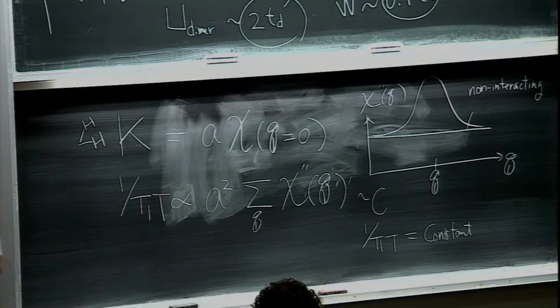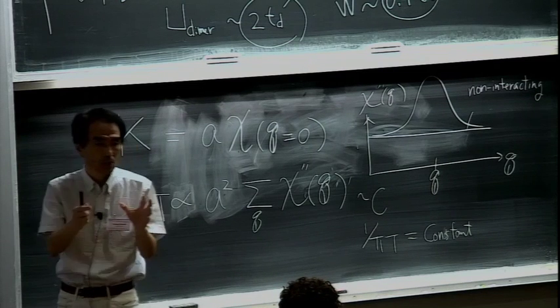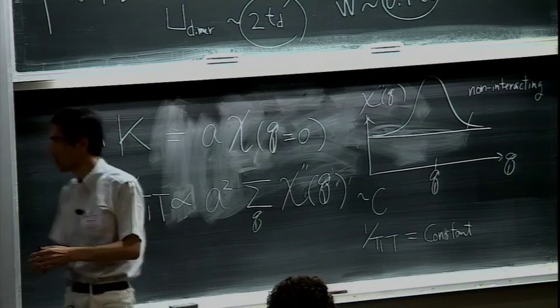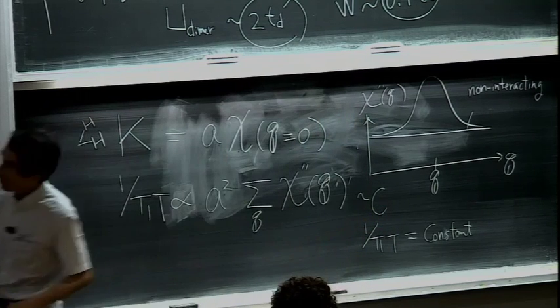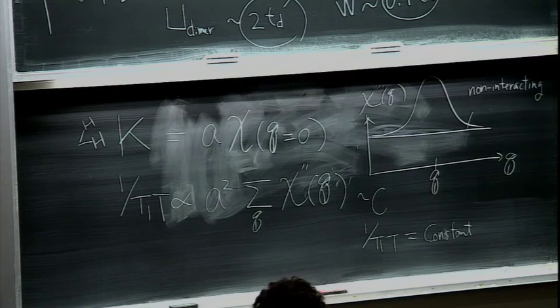So to look into the nature of the spin magnetism or electron spin dynamics, we have to do carbon-13 NMR. Carbon-13 is located at the center of the molecular orbitals, so this coupling constant is large. This is the temperature dependence of the NMR relaxation rate; 1/T1 characterizes the fluctuating magnetic field. This logarithmic-scale plot is the same data represented on a linear scale—please take a look. Two data sets come from two kinds of carbon sites.